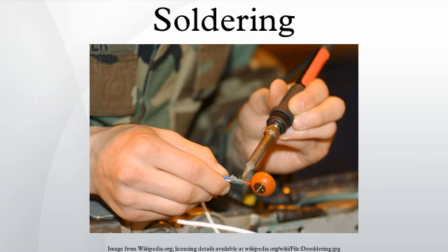Soldering defects. In the joining of copper tube, failure to properly heat and fill a joint may lead to a void being formed. This is usually a result of improper placement of the flame. If the heat of the flame is not directed at the back of the fitting cup, and the solder wire applied opposite the flame, then solder will quickly fill the opening of the fitting, trapping some flux inside the joint. This bubble of trapped flux is the void.